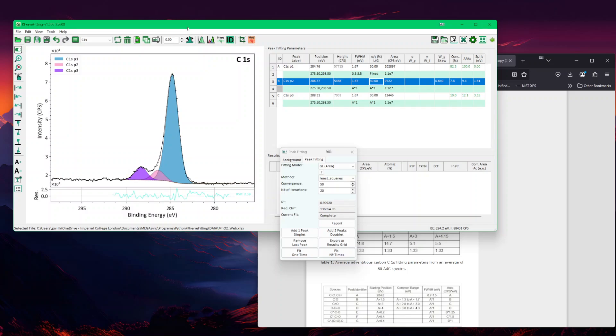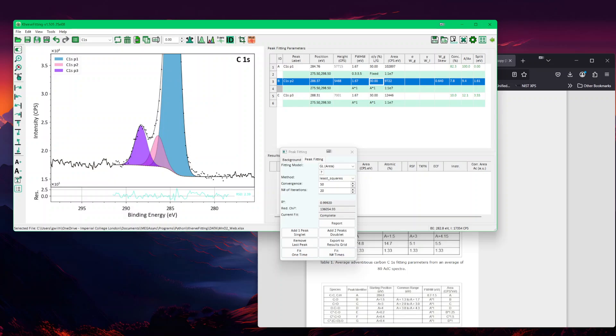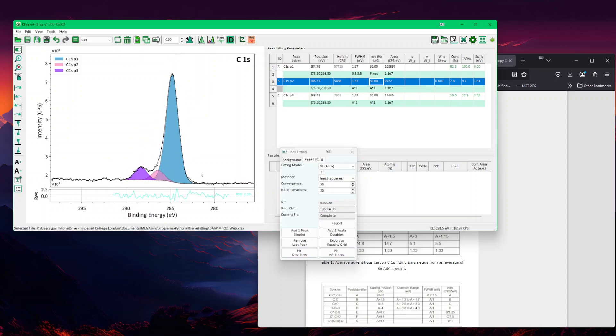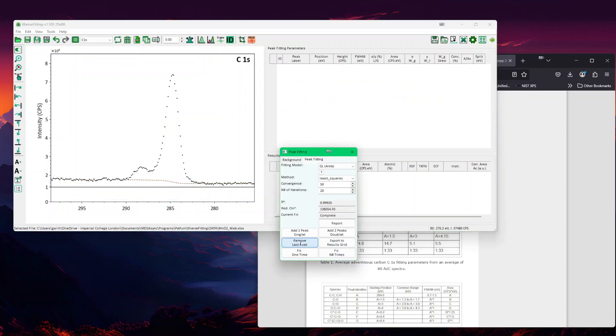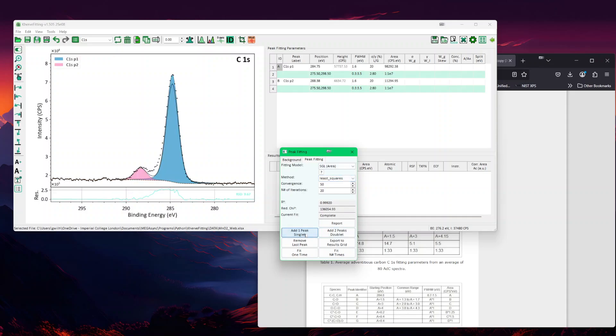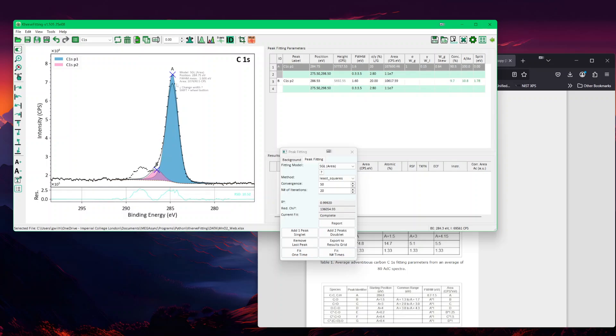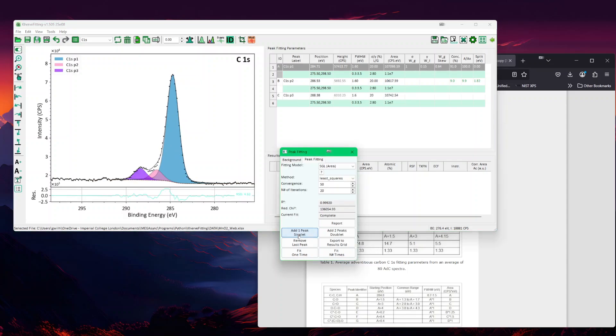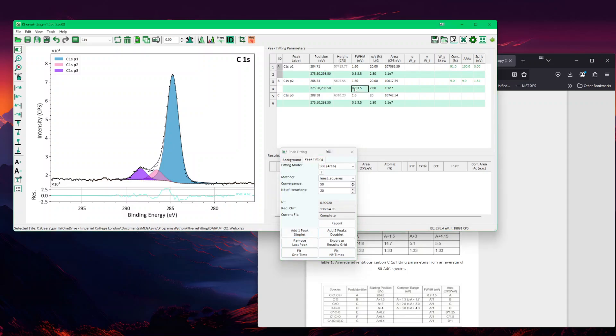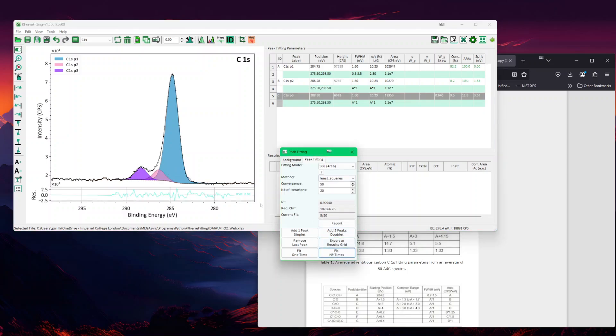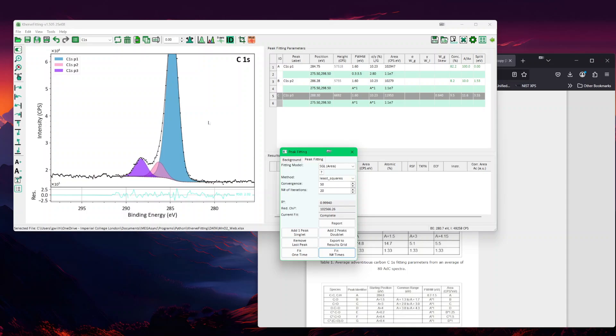But the GL is known to not fit properly at the edge of the peak. This is why I would recommend to use the SGL, which is so close to the Voigt function. Let's go back again and choose an SGL and use the same type of model. Then use exactly the same parameters that we've used for the GL model. Now we would fit. The RSD value went from 2.38 to now 2.02, so it's a better fit than the GL model. Now this is around 10%, that's the best he found.